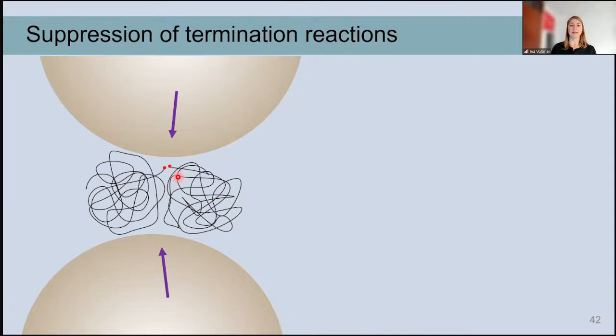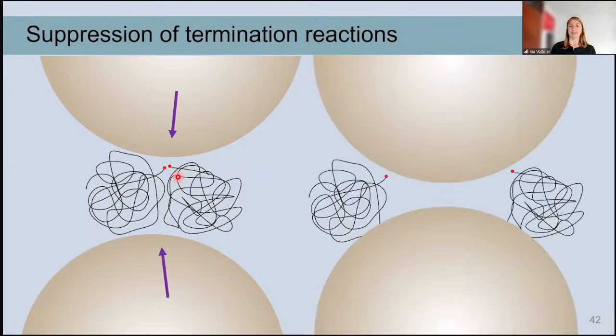However, because these grinding spheres are hitting each other, they can actually displace the radicals and move them away from each other very efficiently. And this could effectively suppress the radical termination reactions. So this could be an effect. This could be the effect that we're observing here, and that would mean that we are actually seeing more depolymerization rather than recombination in our system already.